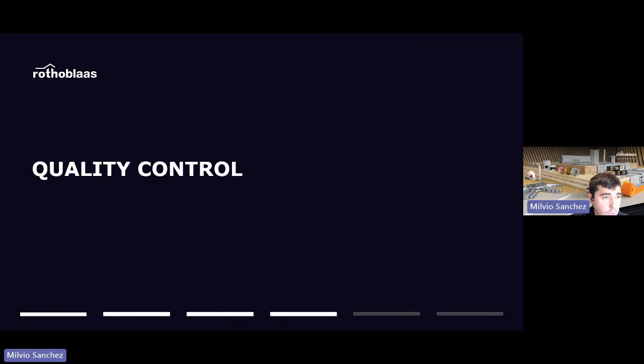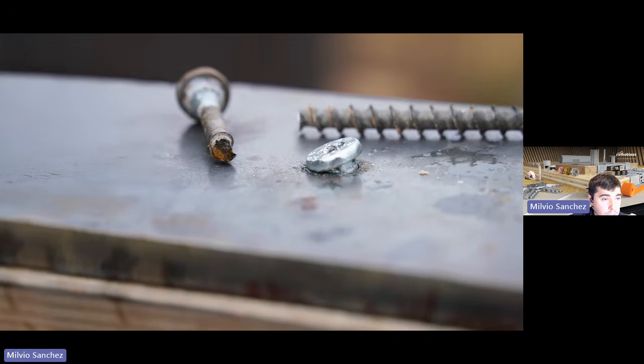Now I have a few slides about quality control. As you see, aesthetically, wood can get compromised and damaged with moisture, it's clear, but the structural components may also suffer from failures. In this case, we have a failed screw in a very critical condition where we are installing a thick plate with wood. The screw is under corrosion, there is presence of water, the screw is already misaligned, and let's say this is over torqued.